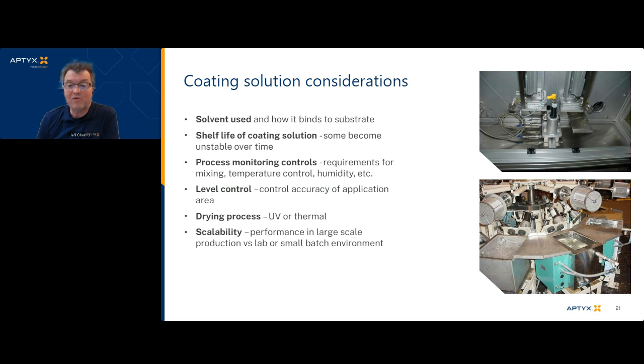And then after we applied the vacuum in an oven condition, we were able to reapply thermal conditions to it at a higher temperature. And at that point, we were able to successfully prove that all the solvents were adequately removed. And we basically mimicked what they were taking several days to accomplish within their original process that they developed. So it's interesting that processes come to us that our customers believe to be mature, but then we challenge them to discuss how we could optimize that to make it truly something that they could implement in a production environment going downstream, that's going to be manageable, and optimize their success and also their quality.